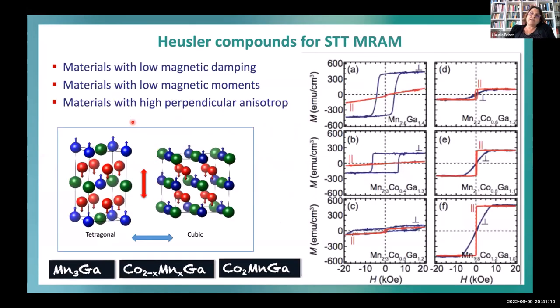And this is interesting because then you have this additional magnetocrystalline anisotropy. In our original work, where we worked a lot on the manganese-rich Heusler compound, Stuart wanted to have material for spin transfer torque. And for this, he wanted to have magnetocrystalline anisotropy and very small moments. And in this compound, you can really nicely tune. If you start here with manganese-rich, it's a hard magnetic material with a nice hysteresis, so you dope in cobalt, you reduce the magnetization even further, so you can have even giant coercive fields, and then if you go to the more cobalt-rich side, you end up with a cubic structure and a soft magnetic material.